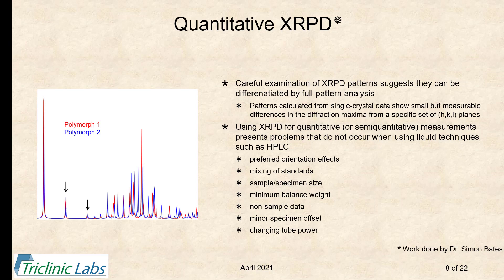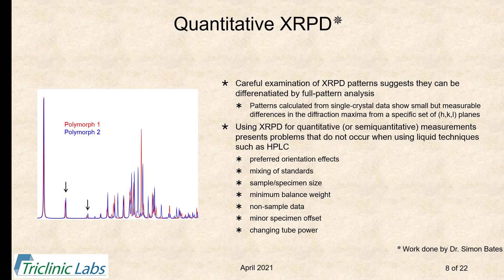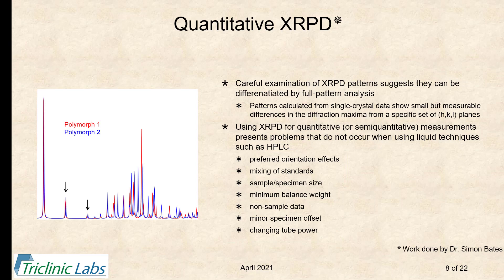By looking carefully at the X-ray patterns calculated from single crystal data, we can notice that polymorph two has freestanding peaks, and under the arrows there appear to be doublets reflecting small but real differences in peak positions between the two polymorphs. Full pattern analysis of X-ray patterns was undertaken to develop a semi-quantitative, non-validated method to aid in drug product development. We do quite a bit of this work—development and validation of X-ray methods for quantitative analysis of solid mixtures—and there are significantly more challenges compared to liquid techniques like HPLC.